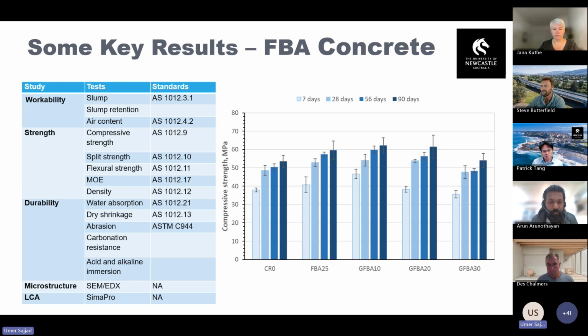So here I am showing the results of compressive strength up to 90 days. We have conducted the test, and you can see that the 10% replacement mixture produces promising results when we compare it with the control concrete.